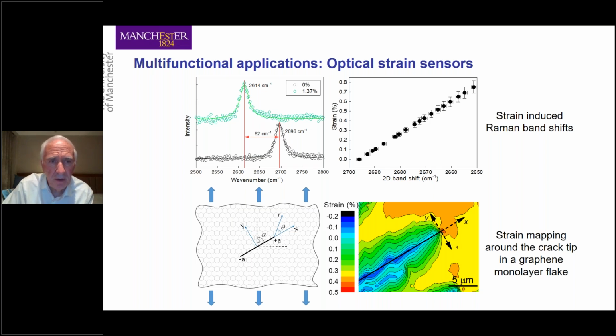This is a sketch of our flake of graphene, and this is a flake of graphene containing a crack. And this is only 5 microns here. And you can see that this is where the crack is. And in the crack region, we have blue coloration indicating low strain. Then right at the crack tip here, we have a red coloration indicating strain or stress concentration. So you have the ability with great precision to map out local strains in graphene. And I think it's pretty easy to envisage a situation where you have graphene flakes in a paint type structure, and you can go around and map out local strains in the substrate underneath. So this is essentially how you could make a strain sensor using graphene.